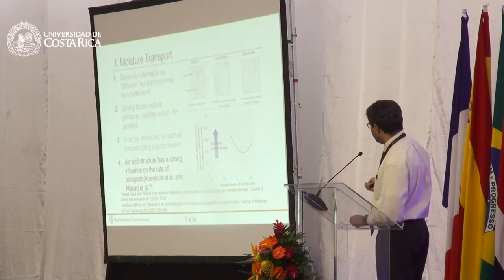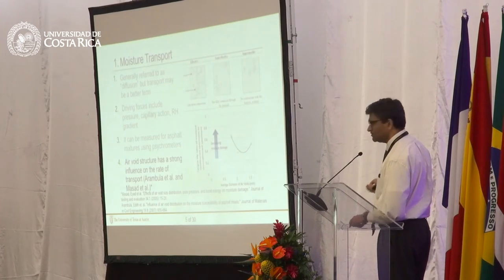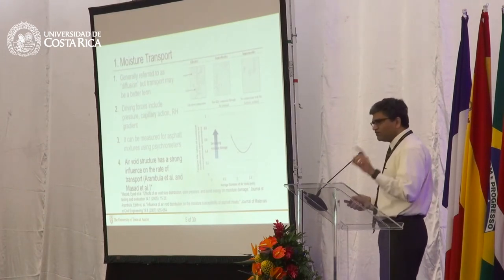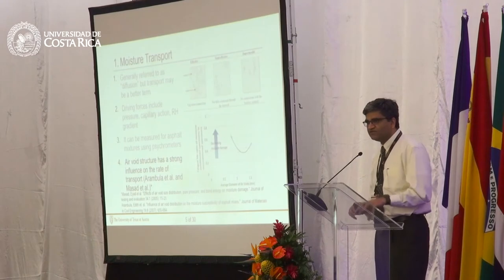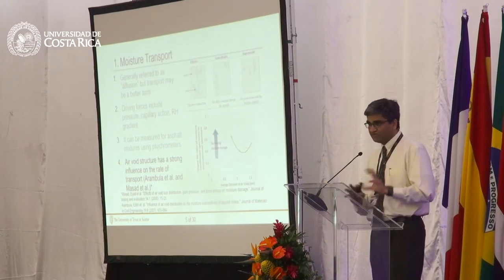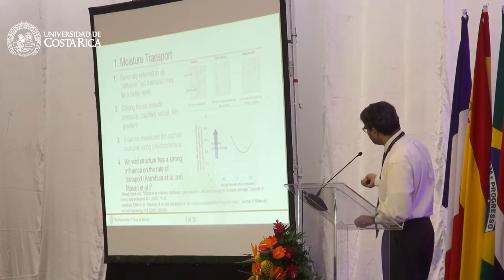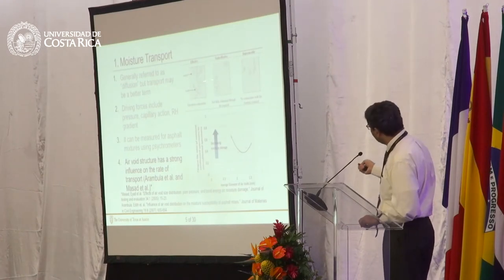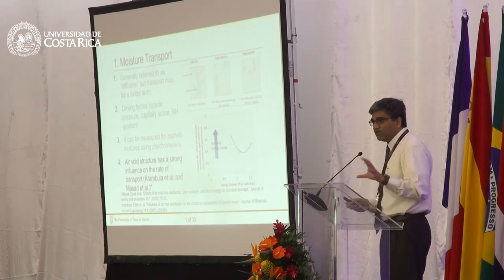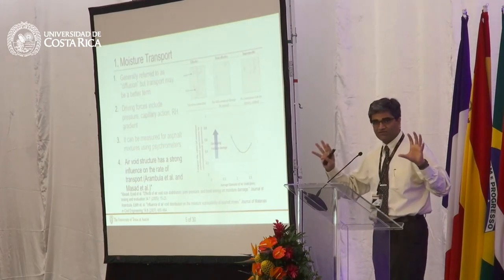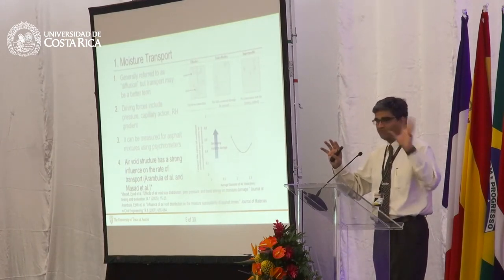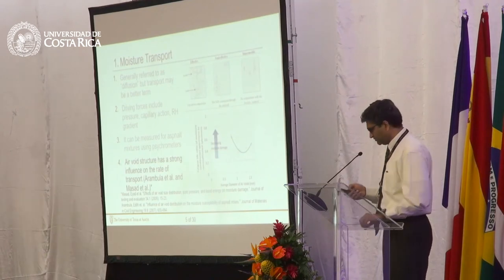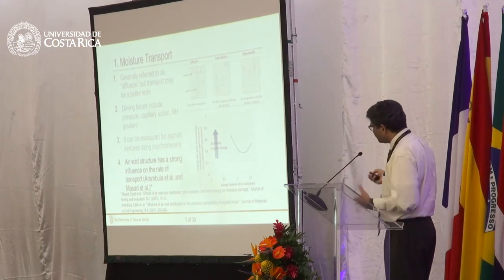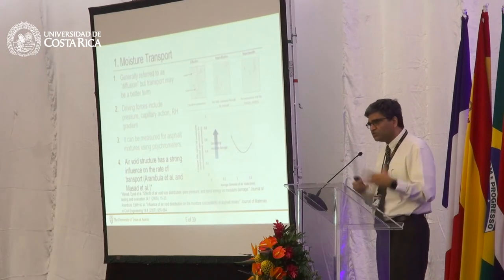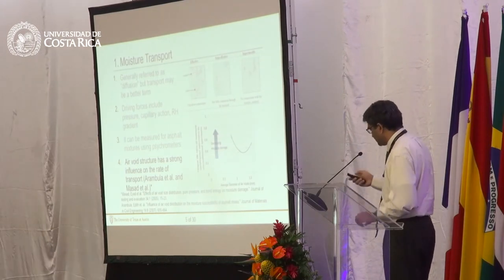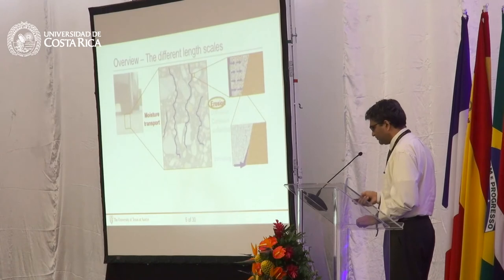One caveat I would like to mention here is that this study was very carefully controlled. Averages can be misleading. You can have several mixtures with the same average air void but different air void structure. So this really is not the best metric to capture whether or not this happens, okay? Because you can have two different mixes with the exact same average air void, but that average can be distributed in a very open structure or a very closed structure. So that's something to think about. And you have tools like X-ray tomography now that you can use to explore whether or not this kind of mechanism is a problem.